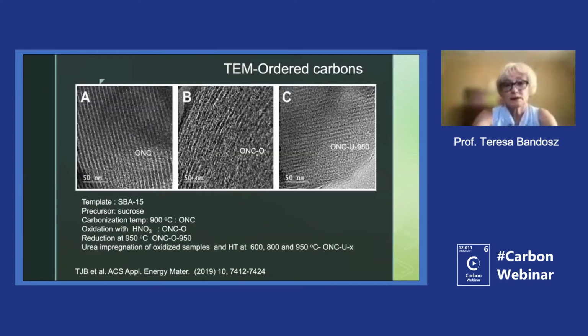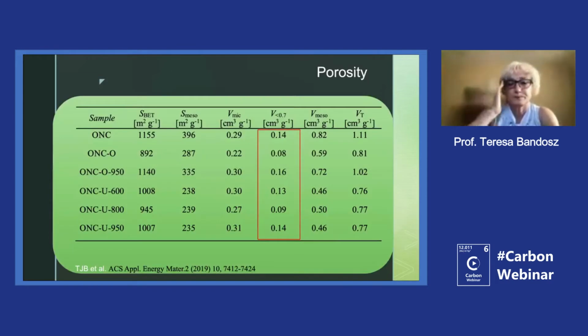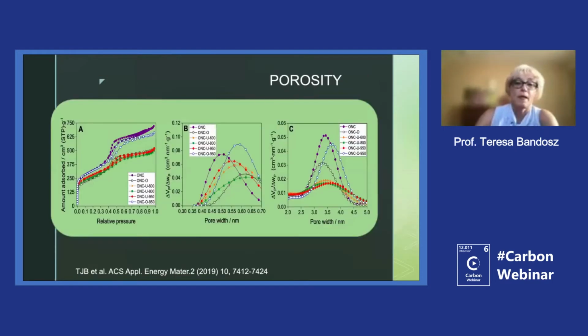So after this, we decided to look at ordered carbons. Of course, they have the mesopores, which should help with the reduction. We synthesized them from sucrose, then we oxidized the sample, treated it with urea and heated it at different temperatures to introduce nitrogen. And here are the porosity results. So apparently we changed the volume of ultra micropores, and of course the surface was also modified. And that volume of ultra micropores was very important for us.